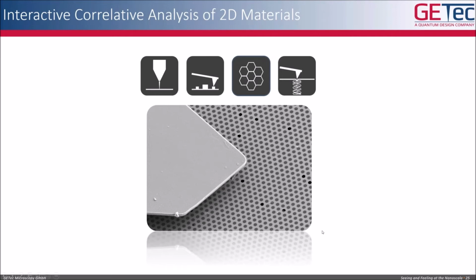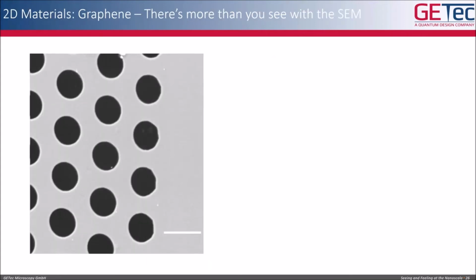The sample you see here is the same one I showed you in the movie, how we can create a correlative image. It's a silicon nitride substrate with holes, and these holes are covered with 2 or 3 monolayers of freestanding graphene. The experiment we performed was to analyze the mechanical properties of these freestanding graphene membranes.